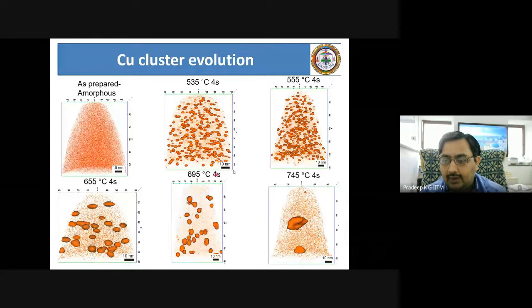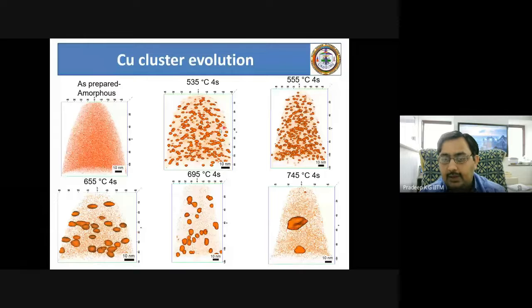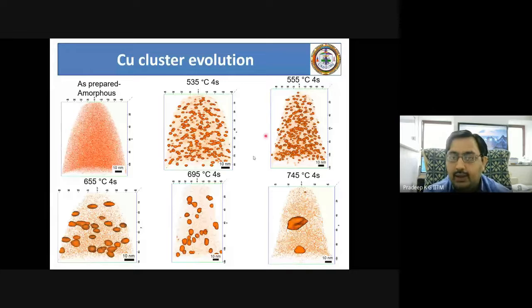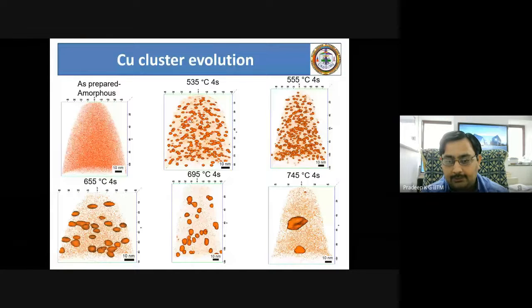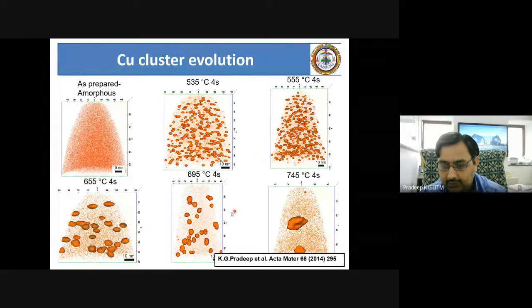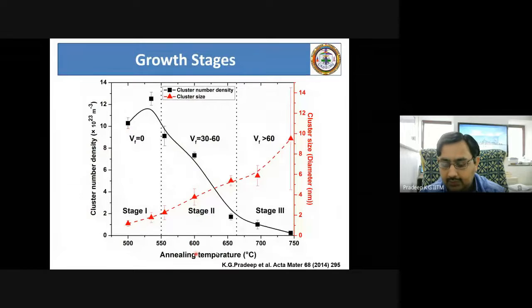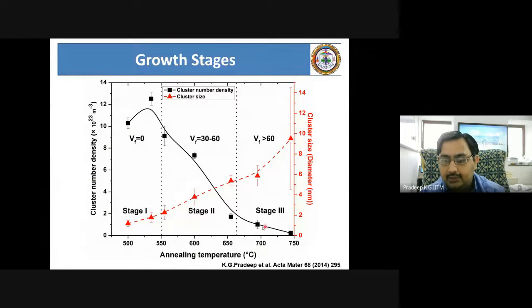Now, as you keep on increasing in temperature, you can see here the size of the copper clusters is increasing and the number density of the copper clusters is decreasing. So this information you can only get from this kind of atomic scale analysis, and I will show you later what happens if you try to see the same information in a projected microscopy. But in principle, one can notice that as we increase in temperature, the cluster size increases, the number density decreases, and it can easily be quantified by this kind of graph where you can see with increasing annealing temperature, the number density is decreasing and the cluster diameter or the size is increasing.